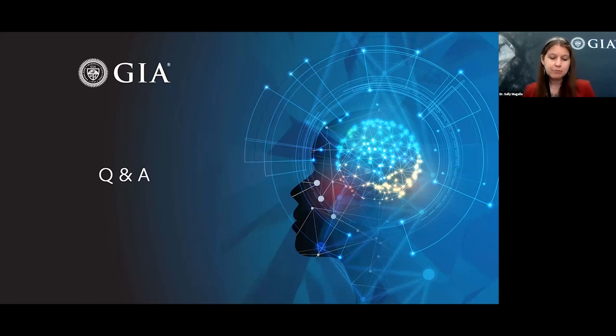But what that does is the radiation causes the carbon to be knocked out of its home position, and it creates a vacancy where there's a lack of a carbon atom where there should typically be one within the diamond lattice. And that creates what we call the GR1 defect. That creates an absorption at 741 nanometers within the red, but it also creates a sideband that goes from the red into the orange and the yellow, which helps create a transmission window within the green to the blue portions of the visible spectrum. Great, thank you.